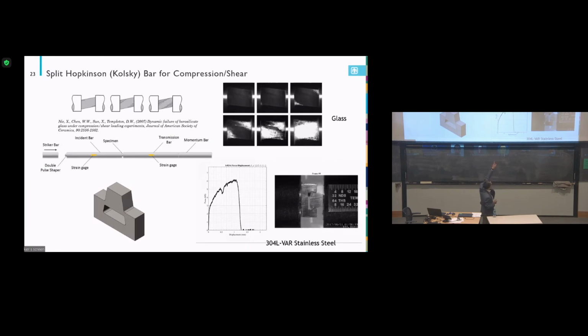So you see the load induces micro cracks during the impact. Then the micro crack grows, propagates, eventually interconnects with each other. Then the whole sample is totally fractured. So that's one way we do the compression shear test. And another example is a specimen we call the top hat. It looks like a hat, like this top hat. So if you impact the sample from here to here, this part and this part are subject to dynamic compression shear.